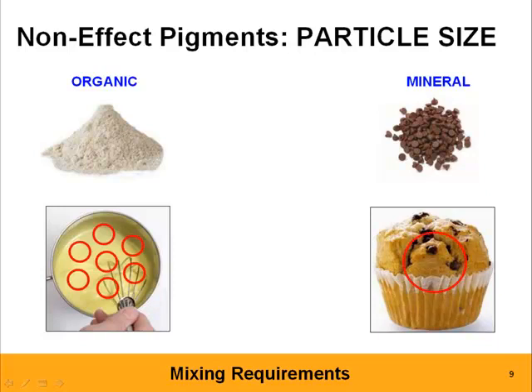The ones on the left, the organic ones, they easily clump together. And if you do not mix them properly, you get concentrations, you get problems with your color distribution in the part. In a worst case scenario, you can get streaks. Or from a color change point of view, if it's not properly mixed in, these concentrates start to leak out. We're losing pigment by pigment, one after the other, and it keeps showing up in the part. So minerals are a lot easier to mix, and a lot easier to color change too in that respect.